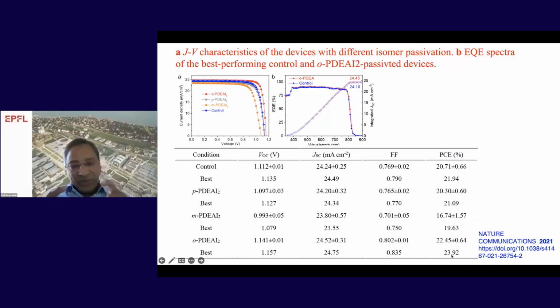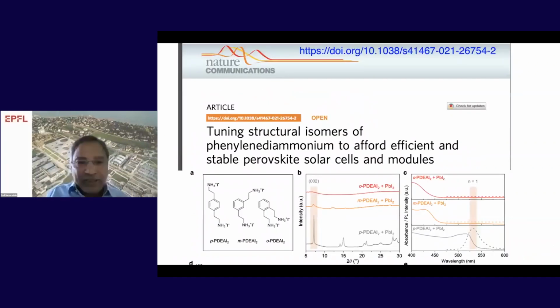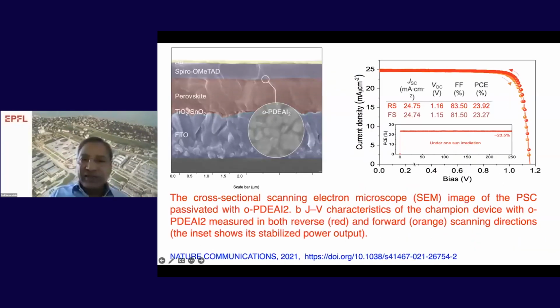So you can imagine by steric reasons that the ortho has a chelation effect. This is the ortho-substituted one. It has a steric effect as well as coordinating ability to the lead, the vacancies of the lead 2+. So that's the reason why the ortho-substituted one gives you the highest efficiency, 24% efficiency.